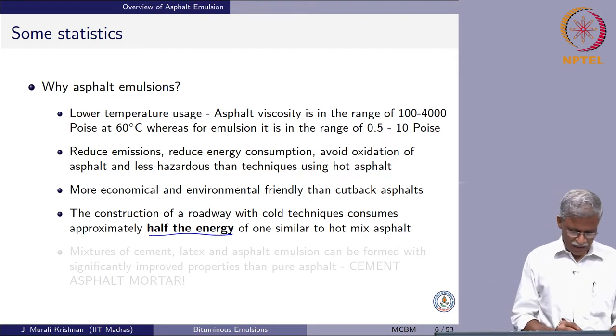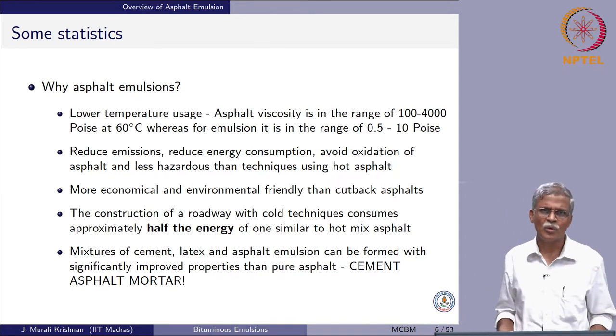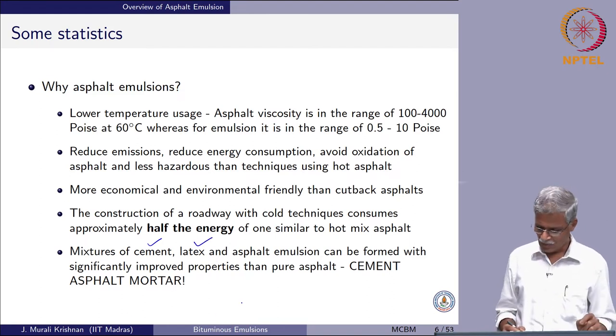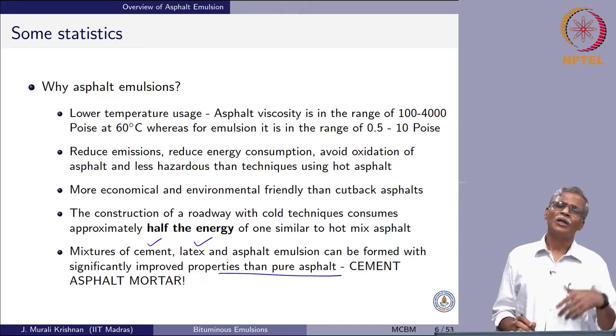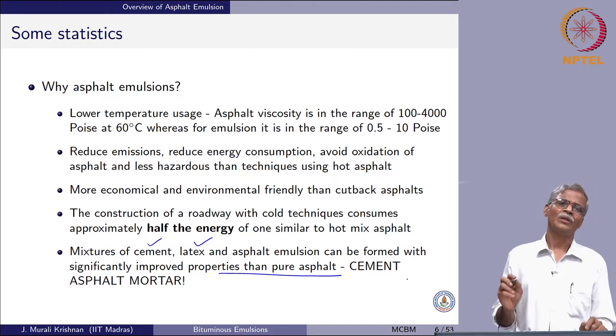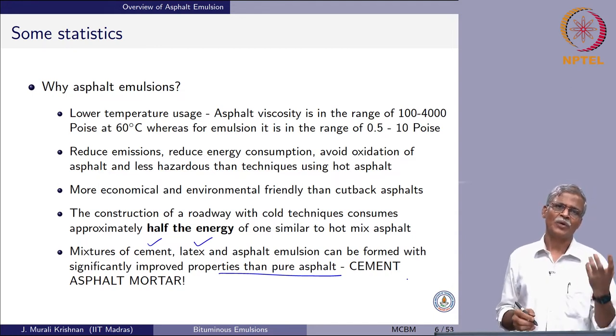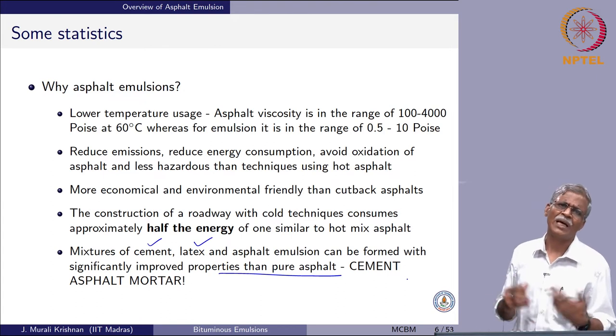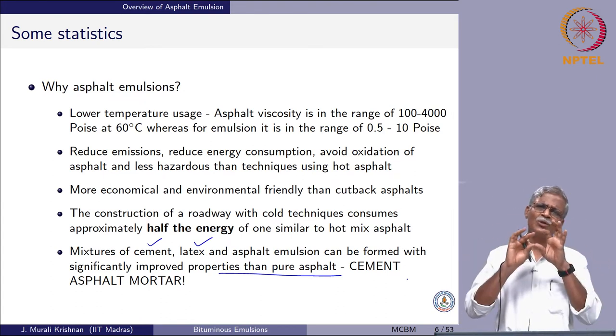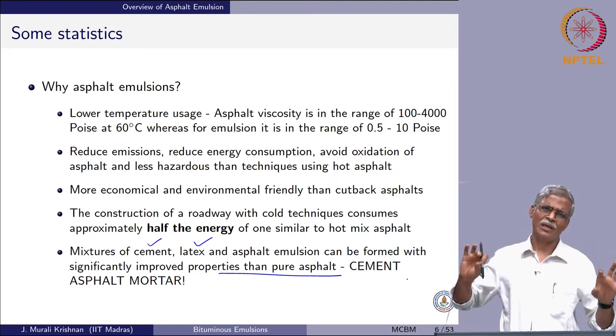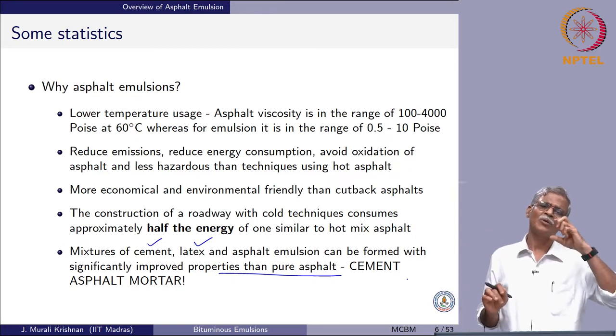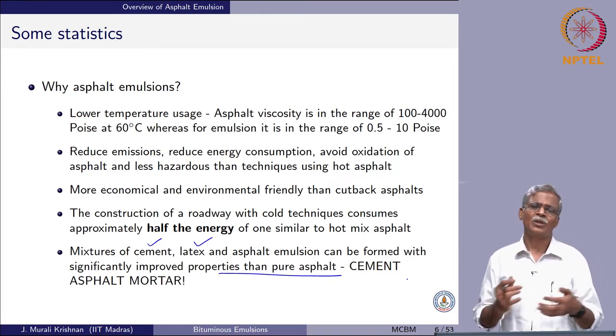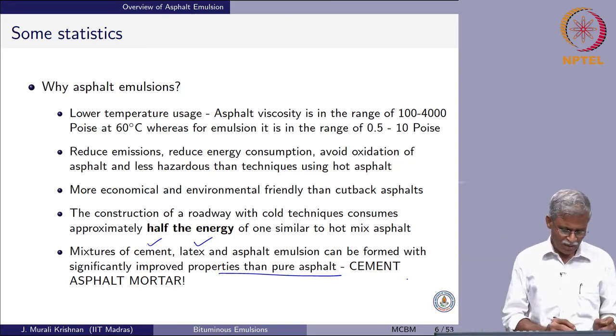You can mix emulsion with cement or natural rubber latex and produce different properties. At IIT Madras, we are working on cement asphalt mortar — we take emulsion, add cement mortar, aluminium powder, defoamer, admixtures, and air-entraining agents to make a product used in the high-speed rail that our country is planning. This mortar replaces ballast below the rail and above the deck slab, acting as shock absorption. There are many many uses related to it.